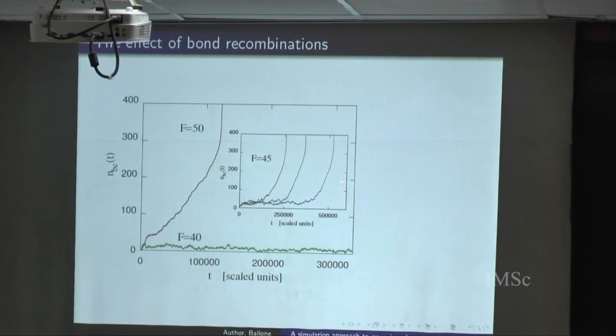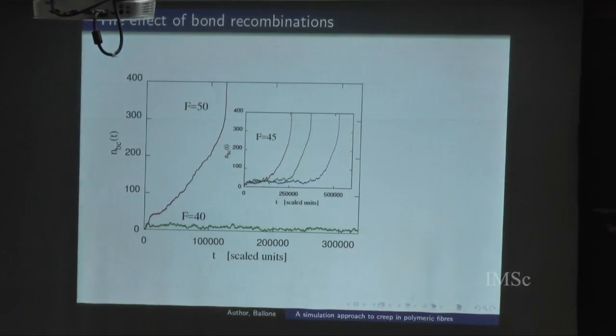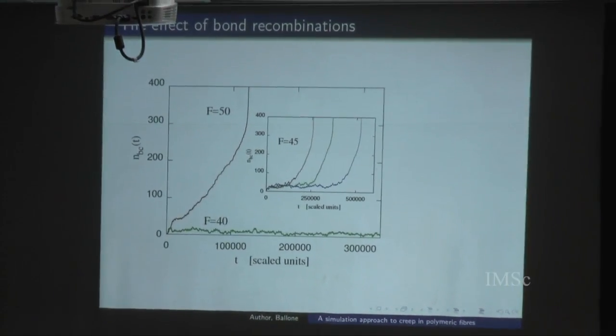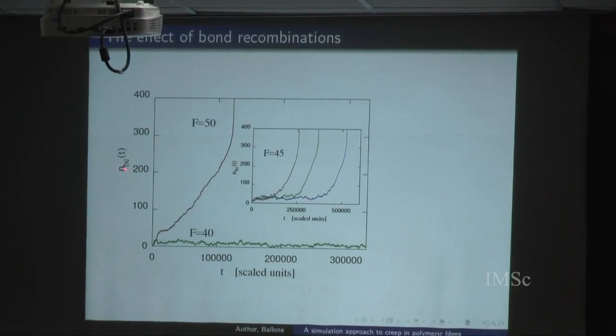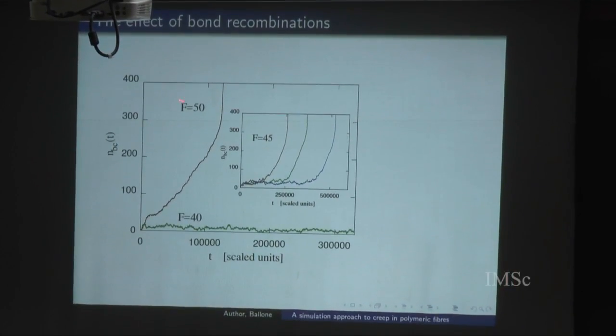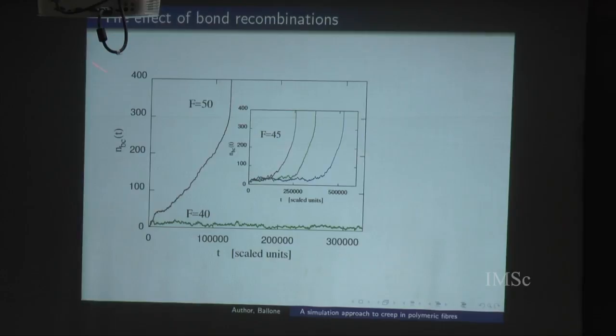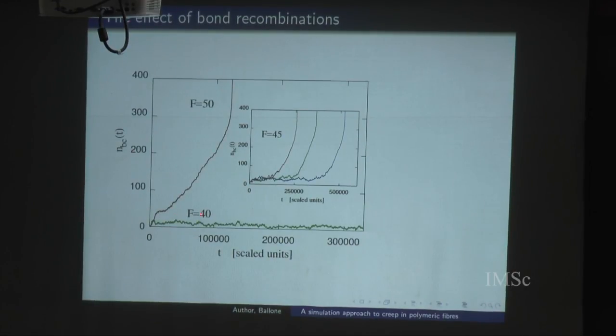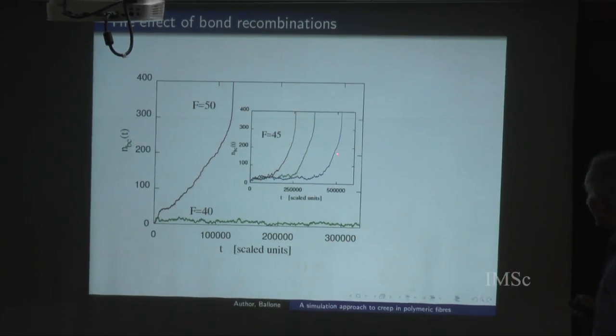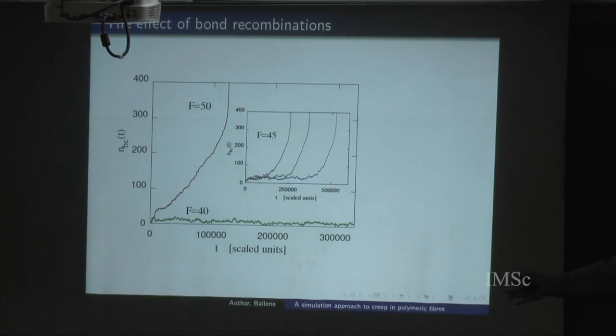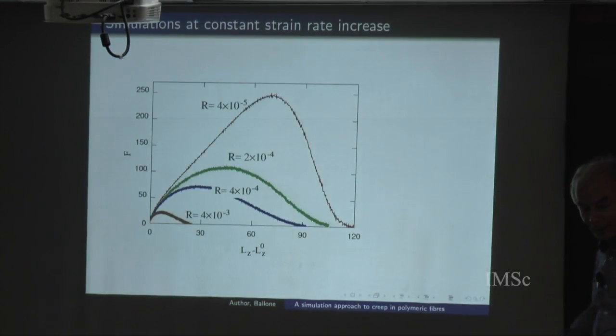And in fact, we really see a transition point, a kind of critical point. This is the number of broken chains. At one load, it reaches the size of the system. At a slightly lower load, instead it is constant. And in between, you get whatever length. So you have huge fluctuations. That means it's almost a critical phenomenon. So those are the simulations at constant